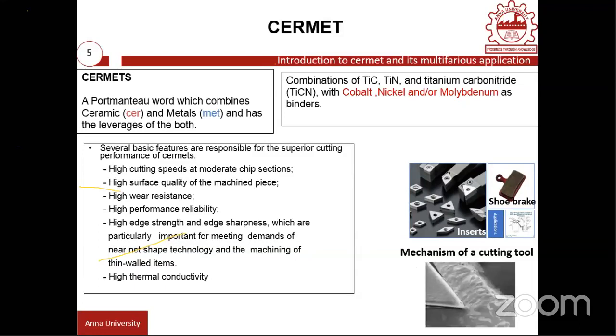As a result, no diffusion mechanism is triggered, no abrasion mechanism is triggered, and no oxidation mechanism will be triggered at this interfacial junction. That means the interface, I am representing the chip tool interface, the area over which the chip is flowing. So high thermal conductivity is another important property the CERMETS has. As a result, the tool life of the CERMETS would be really higher.